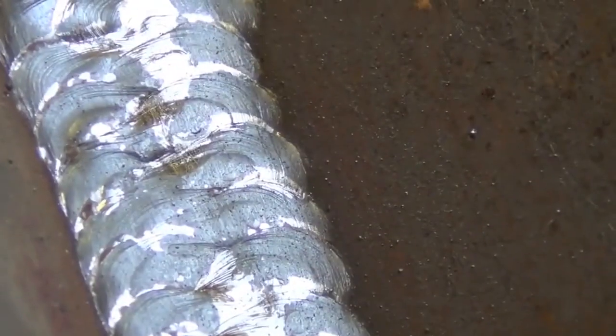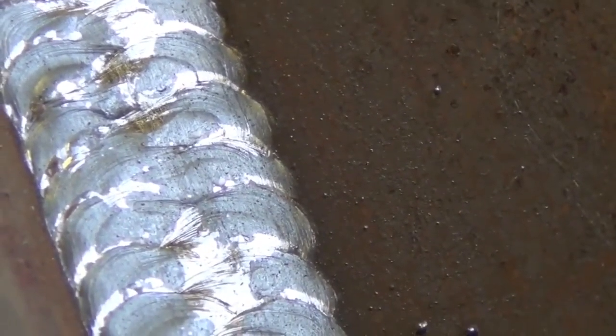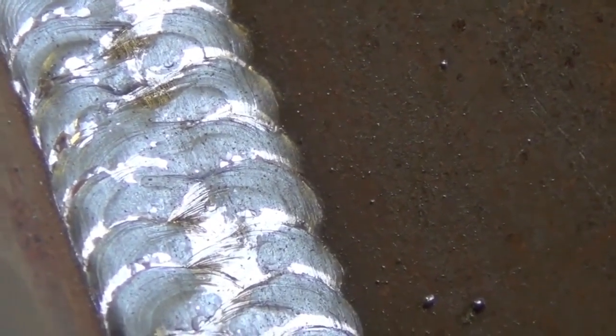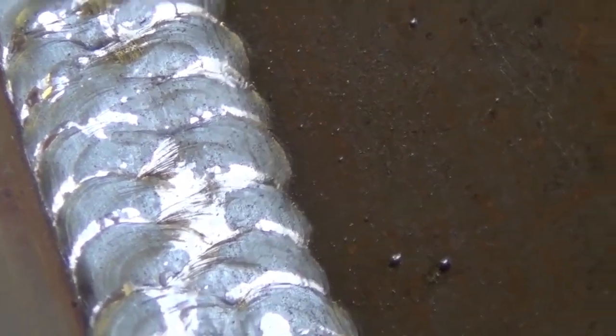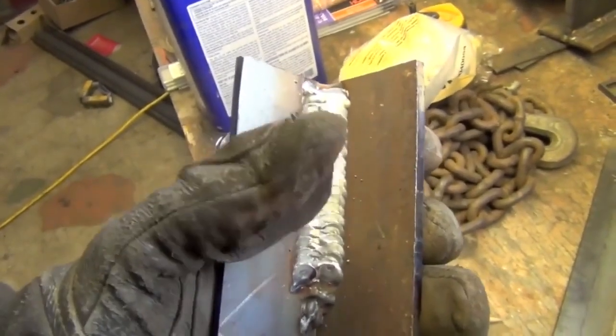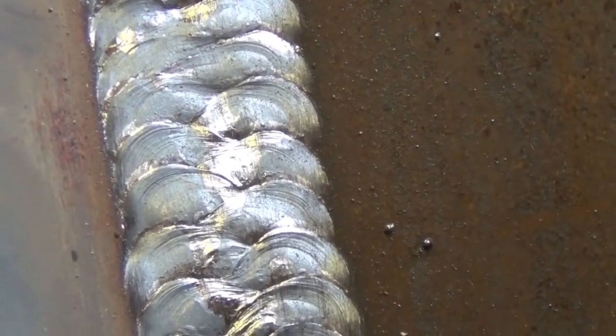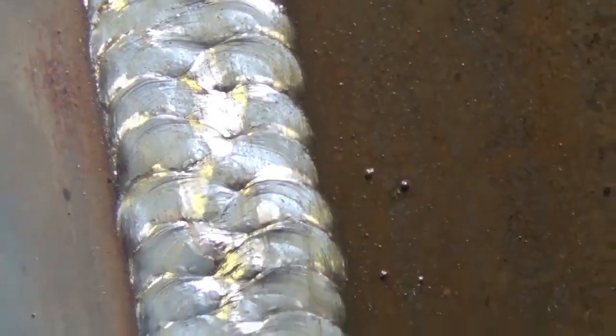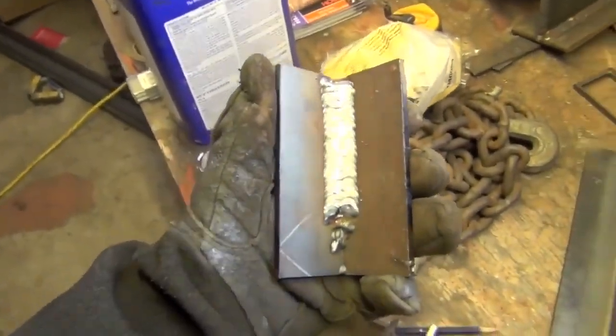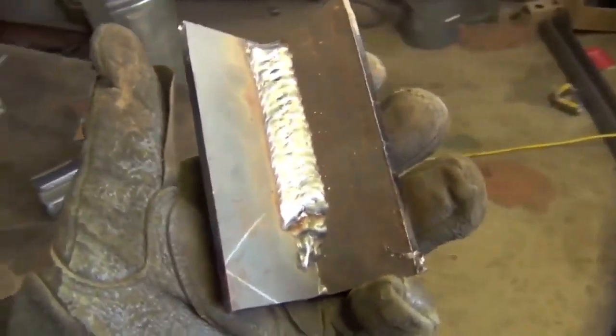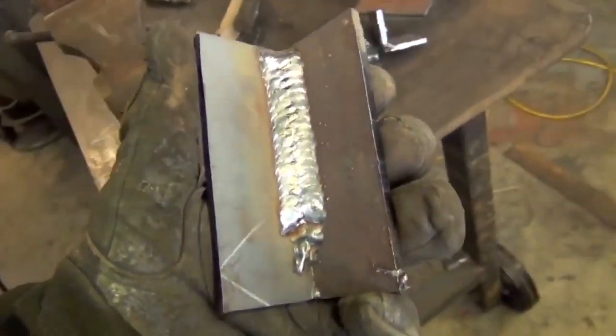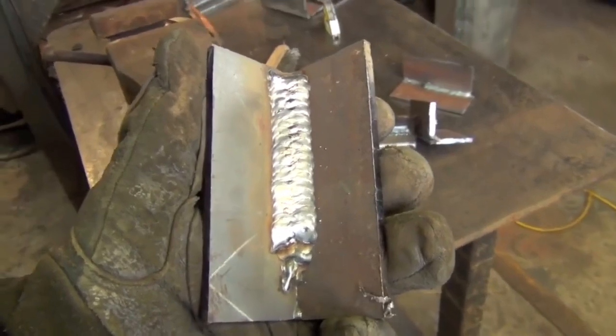And if you look closely at that toe line, you can see all those sharp little indentations. Well, that just means that I'm putting the dots a little bit further apart this way, not so much this way, but definitely this way than I should be. And I'm leaving those little notches, and that's not a good thing because, well, if this weld was ever put under a lot of pressure, that would be a very likely place where the weld would start to fail. So you're going to want to keep that in mind too.